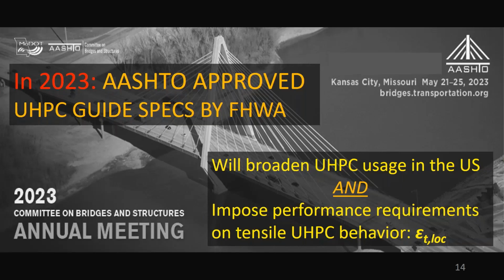Now, something pretty momentous happened a couple of months ago, and that is the AASHTO Committee on Bridges and Structures approved the guide that was proposed by the Federal Highway Administration under the leadership of Ben Graybiel, who's one of the panelists. I think this is a really important thing that will broaden the use of UHPC in the US. And one other interesting thing is that this document imposed performance requirements on the tensile behavior of UHPC because that is so critical to response. Remember this localization strain that I mentioned a second ago? And this was approved unanimously. I was there at the meeting, and it was very interesting that that happened. A few questions here and there, but in the end, unanimous approval.